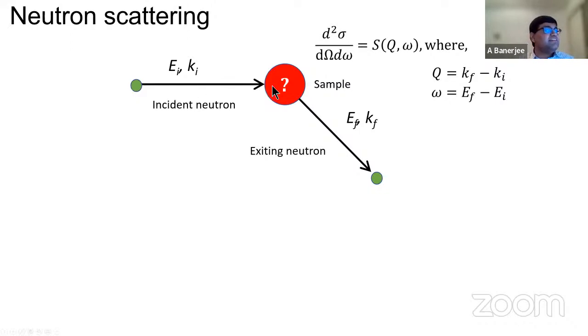So if you have an incident neutron that hits your sample and you then get an exiting neutron, the incident neutron has an incident energy Ei and an incident momentum Ki, and it exits with an exiting energy Ef and an exiting momentum Kf. And when that happens, because the sample has certain allowed energy levels, the neutron basically loses a certain amount of energy and a certain amount of momentum. And you can go to a neutron scattering beamline or an experimental setup, and you can measure that directly.